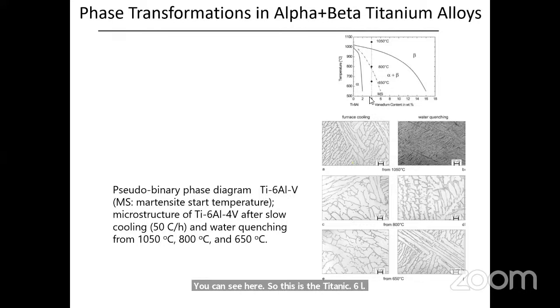And suppose the alloy is heated to above beta transus. Beta transus means, as I already mentioned, the temperature at which alpha plus beta changes to beta phase. So approximately the beta transus temperature for this alloy is 980 degrees centigrade. Suppose the alloy is heated to above the beta transus temperature, for example 1050 degrees, and if you cool slowly from this temperature, like furnace cooling, then you will get a lamellar kind of microstructure. So it is alternate layers of alpha and beta. White areas are alpha and dark lines are beta phase.